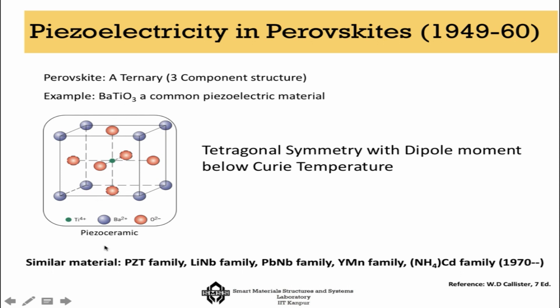Similar piezoelectric effect you will be able to see in lead zirconate titanate, PZT, in the lithium niobium family, in the lead niobium family, in the yttrium manganese family, and in the ammonium cadmium family. The thing that would differ may be the Curie temperature. The Curie temperature tells us beyond what temperature the piezoelectricity would not be there. So the piezoelectricity would be absent in a system.